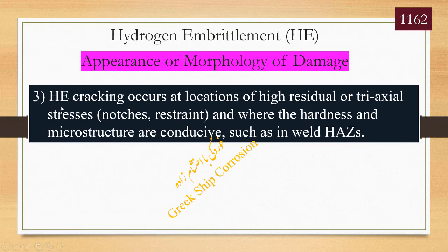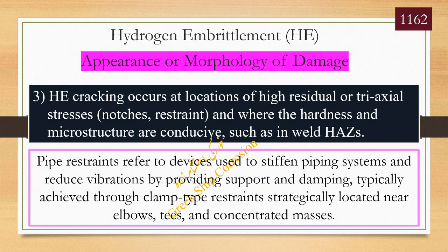3. Hydrogen embrittlement cracking occurs at locations of high residual or tri-axial stresses, notches, restraint, and where the hardness and microstructure are conducive, such as in weld heat-affected zones. Pipe restraints refer to devices used to stiffen piping systems and reduce vibrations by providing support and damping, typically achieved through clamp-type restraints strategically located near elbows, tees, and concentrated masses.